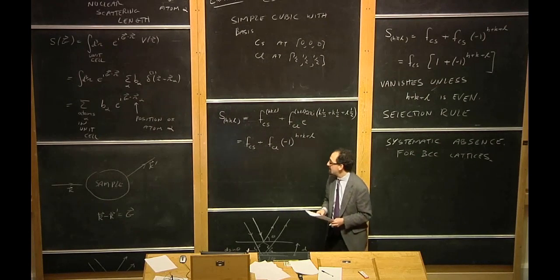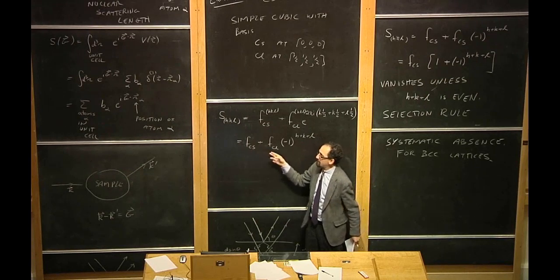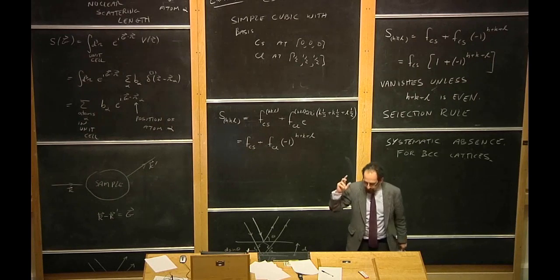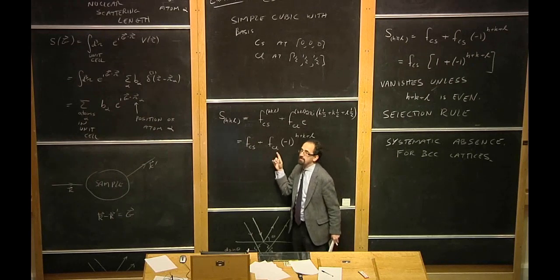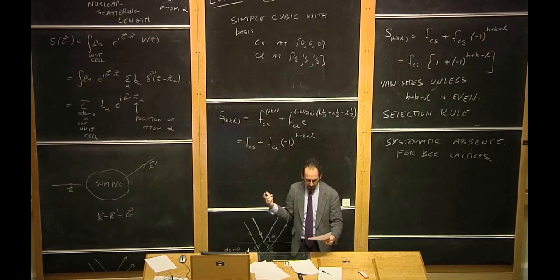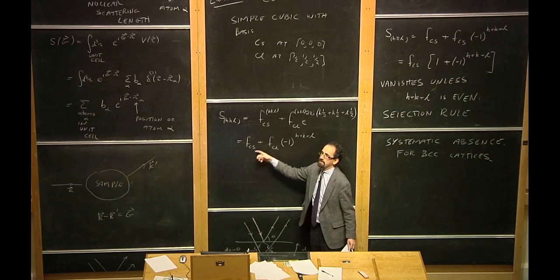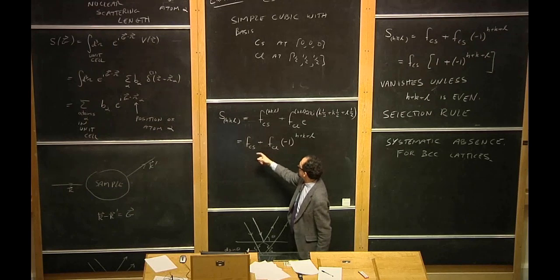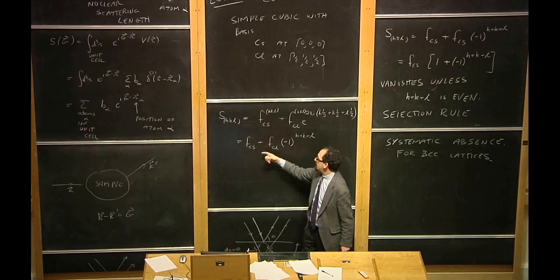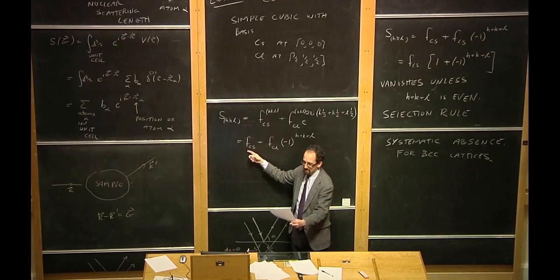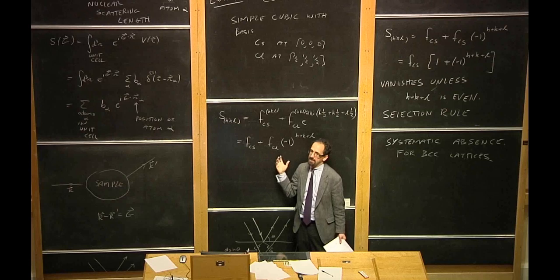Potassium chloride is a very good guess, and the reason potassium chloride is a good guess is because remember that these form factors are basically proportional to the atomic number. And the atomic numbers of cesium and chlorine are extremely different. Chlorine is number 17, and cesium is number 55. So these two numbers will be extremely different. But if you replaced the cesium with potassium, which is right above it on the periodic table and chemically very similar, then potassium has atomic number 19 and chlorine has atomic number 17. So these would be pretty close to each other, and you'd have a near cancellation.